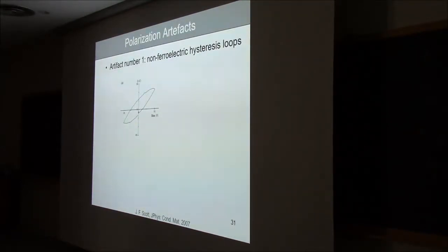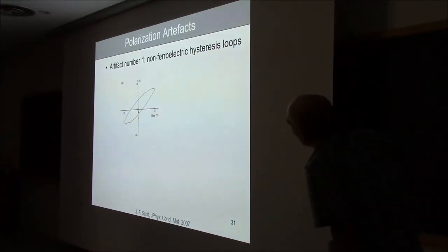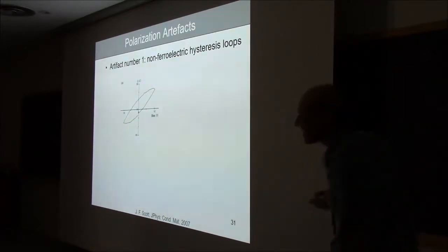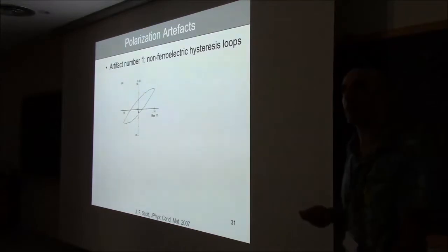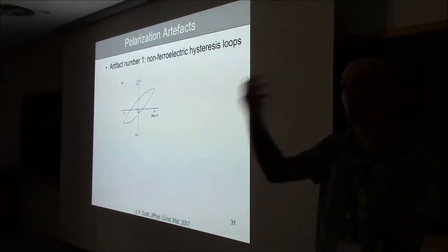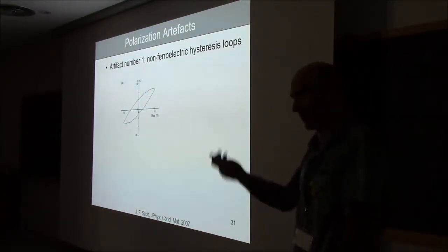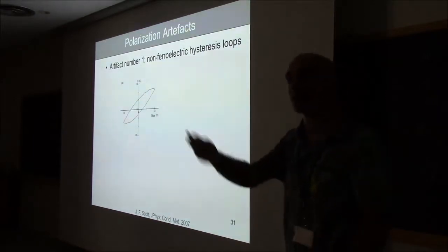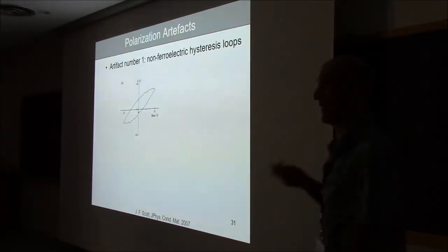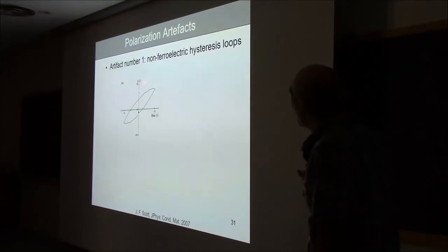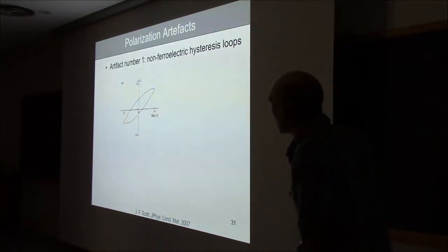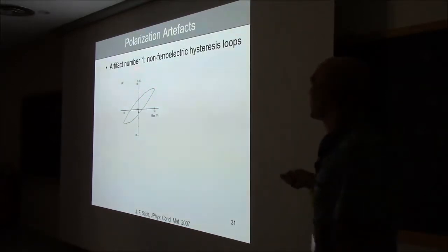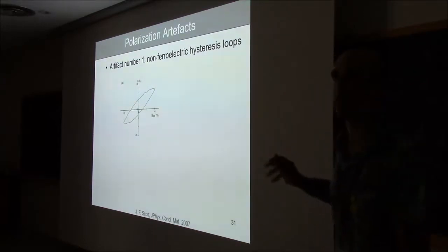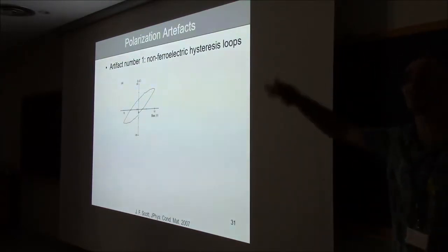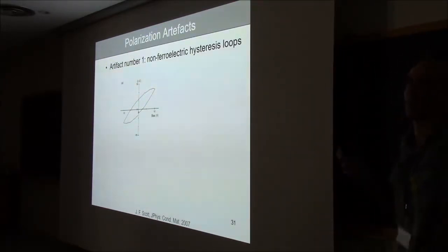Otherwise, people like Jim Scott will ridicule you, will take the piss out of you. Okay? So this is a typical hysteresis loop that you can measure with the commercial Radiant. Doesn't matter which one you use. In most labs we have a machine called the Radiant box. It's a black box, in more senses than one. And it gives you charge as a function of voltage, but of course the software doesn't tell you that this is charge. It tells you that this is polarization. This is basically integrated charge divided by area, and you call that polarization.